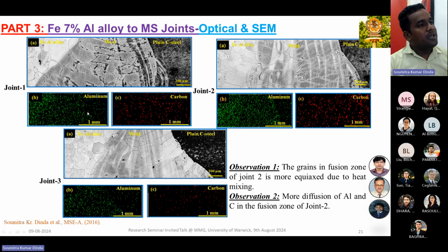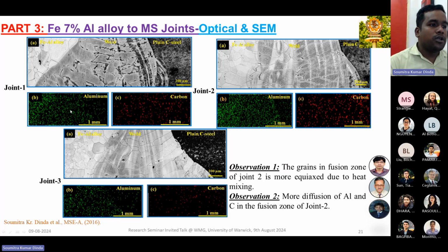Now if you compare these three welding conditions, joint 1, 2, and 3, we can see that in case of joint 3, there is very minimal distribution of the carbon or aluminum in the fusion region. Whereas this distribution is more uniform in case of joint 2, and a little bit good for joint 1. So iron, carbon, and aluminum are the major alloying elements in both cases. That is the reason for getting the worst mechanical property, because of the poor distribution of the alloying element throughout the fusion region for joint 3.